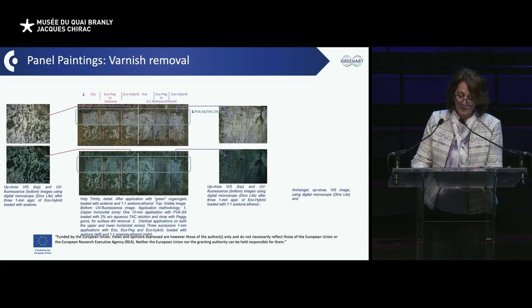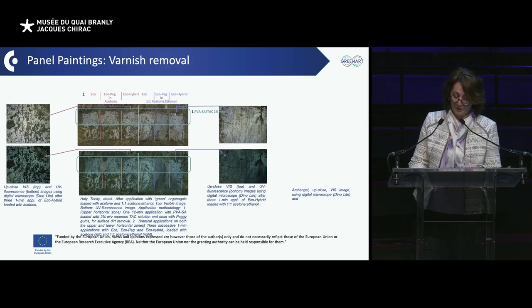Okay. Now let's talk about varnish removal. We aimed for a green approach utilizing organogels loaded with acetone and a 1:1 acetone-ethanol mix. To ensure a clean starting point, we first pre-cleaned a horizontal section with PVA-SA hydrogel containing 2% TAC solution, effectively removing the surface dirt. Then we applied our organogels vertically, covering both this pre-cleaned area and an adjacent untreated section. We opted for successive one-minute applications for each gel.